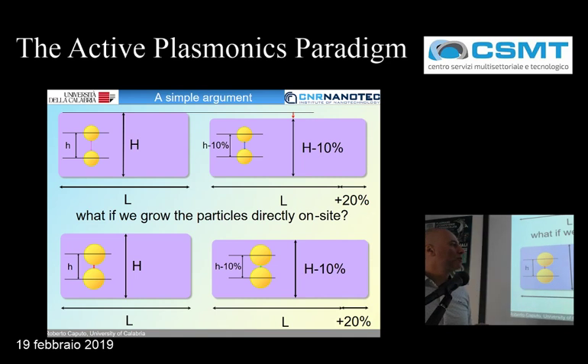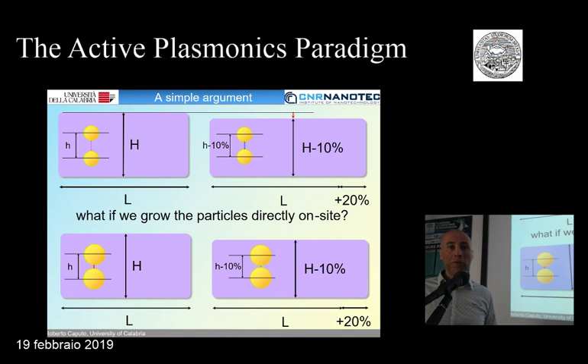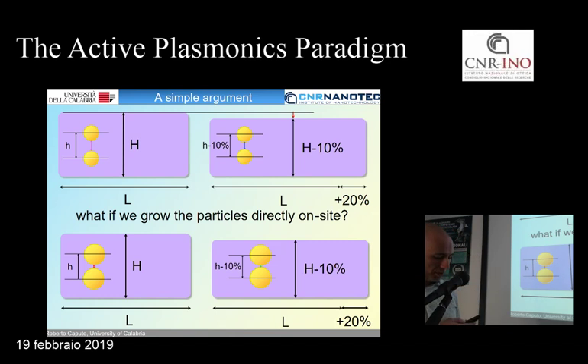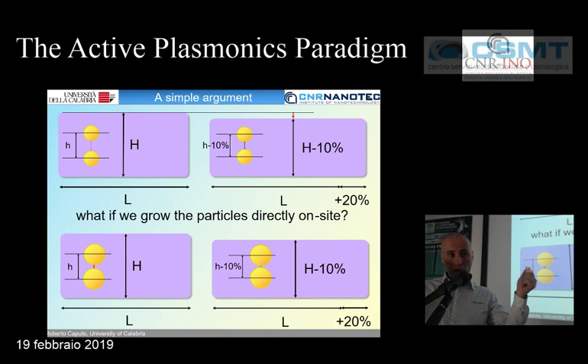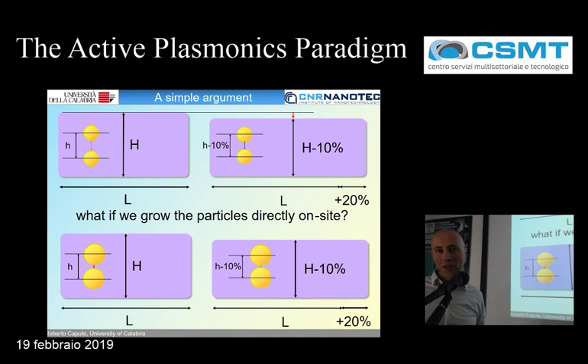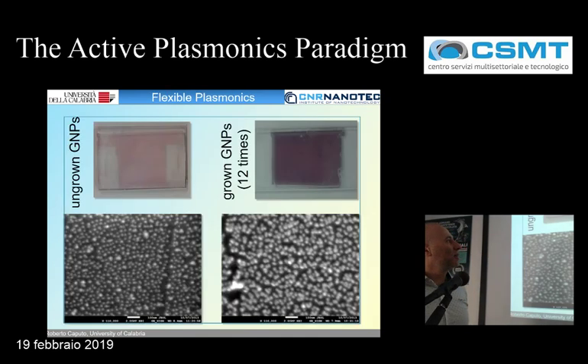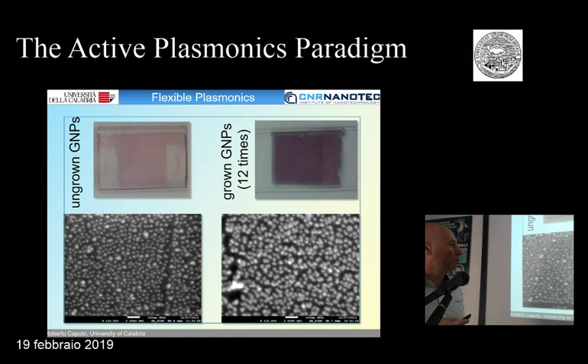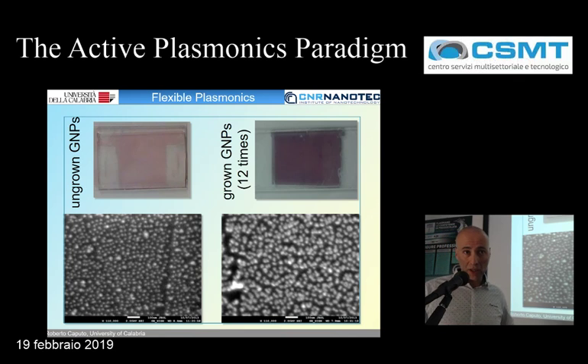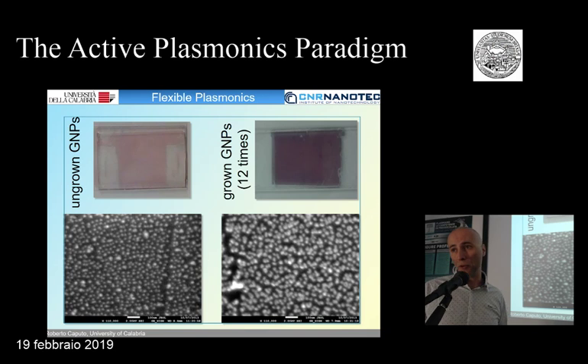So the point was to try to grow the nanoparticles locally before making the experiment. With a chemical procedure, this is possible, and this is what we did. By growing the particles, you start from a kind of pre-coupling condition between them. And when you stretch the material, they go very, very close to each other and induce the coupling you want. So this is the example of the sample without and with the growing procedure. You can see that the color of the sample, the macroscopic image, changes, because in this case the particles are bigger and they are also closer. So you have a different color because of this pre-coupling condition.